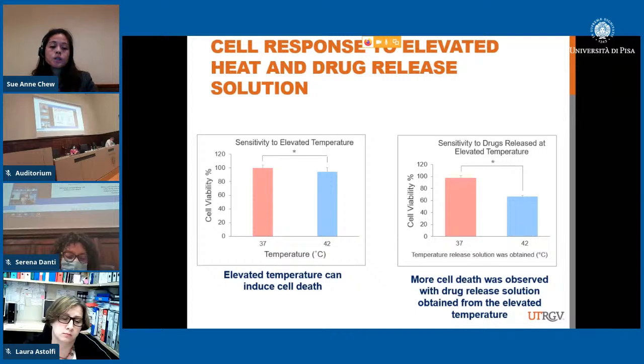And then the next thing we did was two cell viability tests. The first one is a hyperthermia test. We wanted to check how the cells do at physiological temperature compared to an elevated temperature. And we saw that the elevated temperature can induce cell death, which is expected because magnetic hyperthermia uses that temperature. And then we wanted to see whether the drug that gets released at 42 degrees Celsius is going to kill the cells and also maintain its bioactivity. We were worried that the 42 degrees Celsius would deactivate or degrade the minocycline. And here we saw that, at 42 degrees Celsius, the drug release is able to kill the cells more than at 37.